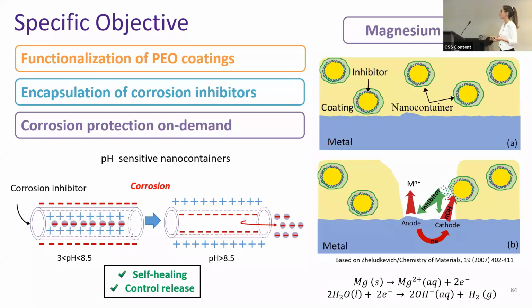So when magnesium corrodes, there's a local increase of pH as a consequence of the cathodic reaction, and this will trigger the release of the corrosion inhibitors that will act locally at the anodic and cathodic sites, inhibiting corrosion propagation. Therefore, the corrosion inhibitors will remain encapsulated while the coating is intact and will be released to the media when detecting this electrochemical activity.